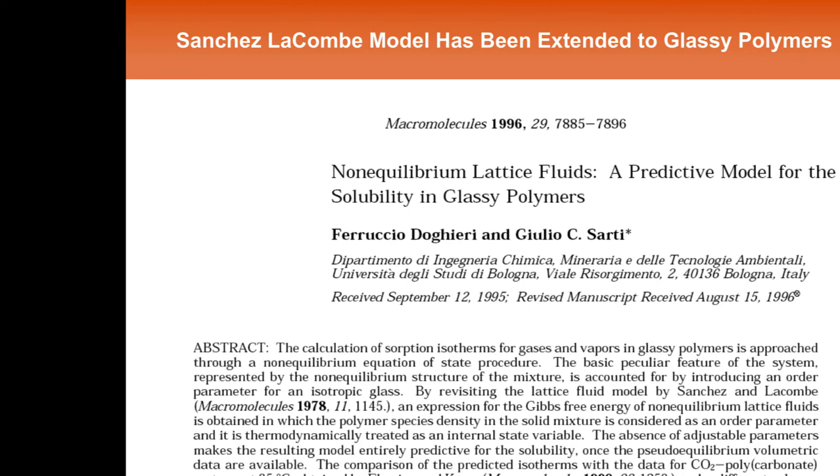If you were to imagine that you are permeating methane through a membrane of this material, and I now start to co-permeate just a little bit of butane, what do you think happens to the methane flux through the material? Yeah, it can drop an order of magnitude, right? So a little bit of butane in the feed gas to this polymer can kill the methane flux, because most of the transport in this particular polymer is going through those huge amounts of the Langmuir sites.